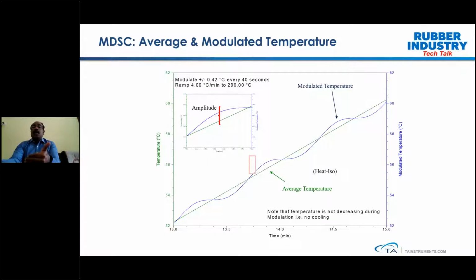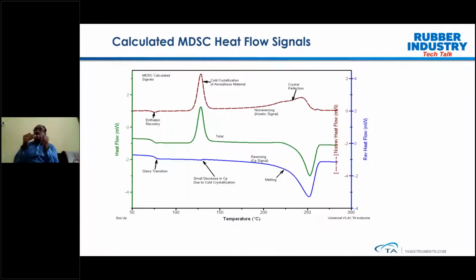And this way, what's happening is the modulated DSC will give three signals. The first is the total heat flow, which is similar to the normal heat flow you get for the standard heating rate. But apart from that, you get two more heat flow signals. One is the reversible heat flow, that is the blue curve, and then the non-reversible heat flow, which is the brown curve.